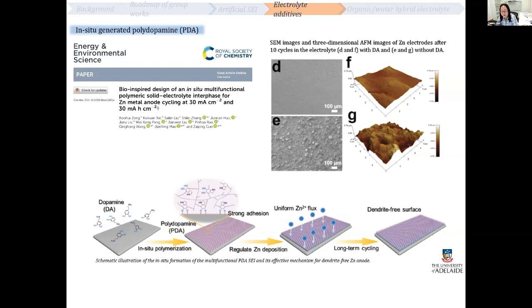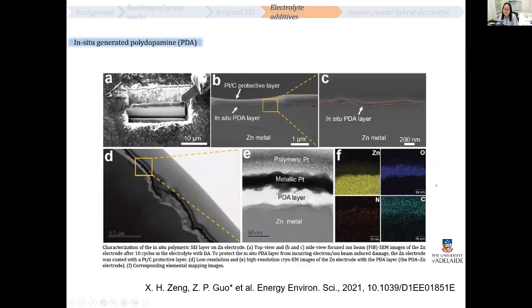the zinc anode. So inspired by the adhesive property of dopamine, in this case, we employ dopamine as the electrolyte additive. During battery charge discharge, this dopamine will in situ polymerize on the zinc surface. This surface layer has strong adhesion, which guides uniform zinc flux and achieves a dendrite-free surface. From the SEM and AFM images, we can clearly see with this SEI, the zinc deposition is much more uniform and the surface is much more smooth compared to the bare zinc anode.